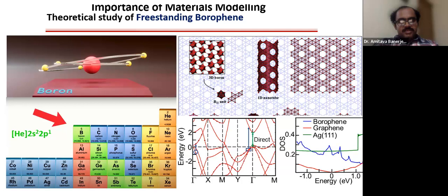Now let me bring in the supercapacitor topic that has been discussed by Dr. Pranay, and he said that borophene could be an excellent material in the supercapacitor, but why should it be? If you see, the supercapacitor is mostly based on the electric double layer mechanism, where people mostly use porous carbons or graphene as an electrode. The specific capacitance of graphene has been measured nearly in the range of 130 farad per gram in the case of aqueous electrolyte, and if you use some ionic liquid, it will be about 90 farad per gram. Graphene can also have a very long cycle life, but the total capacitance of graphene is limited by its quantum capacitance, and that is due to its low density of states near the Fermi level that you can see in the figure.